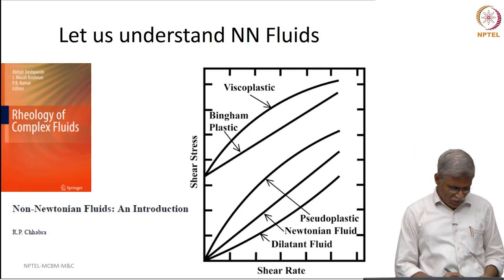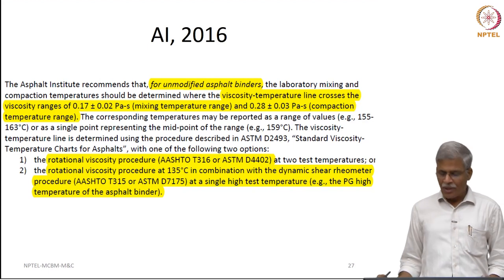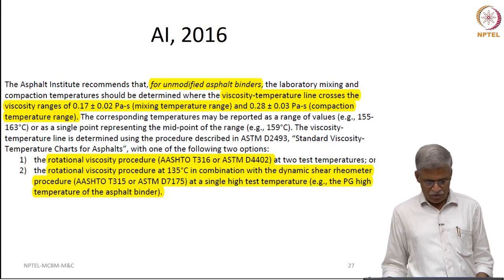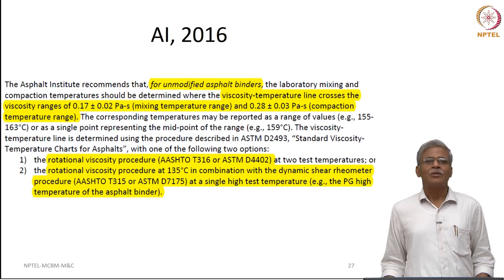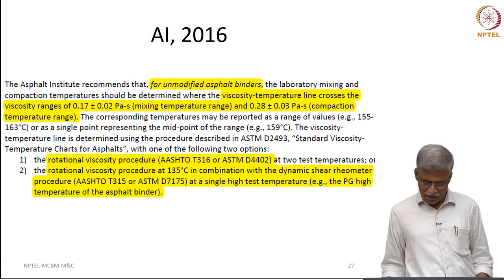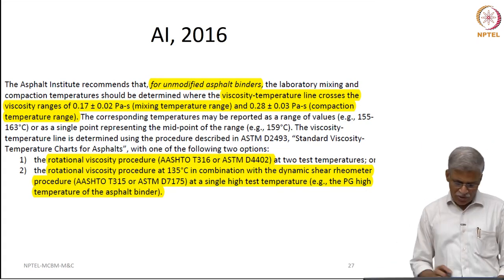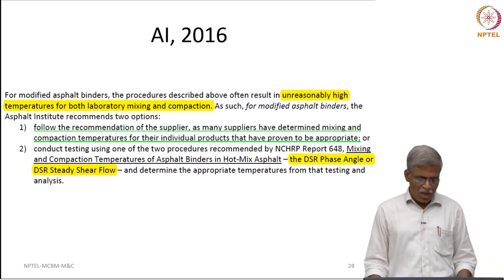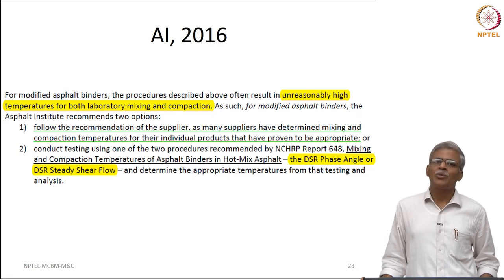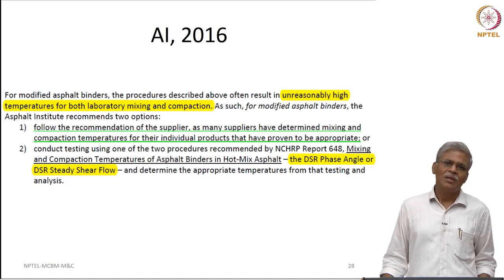In fact, what we are able to say — if you go back and read this — is that the viscosity for the mixing temperature range is 0.17 ± 0.02 Pascal seconds, and 0.28 ± 0.03 Pascal seconds for the compaction temperature range. You can either prescribe the temperature as a range or as a specific value. Now, what really happens when it comes to modified binders — these procedures actually result in often unrealistic values for modified binders.